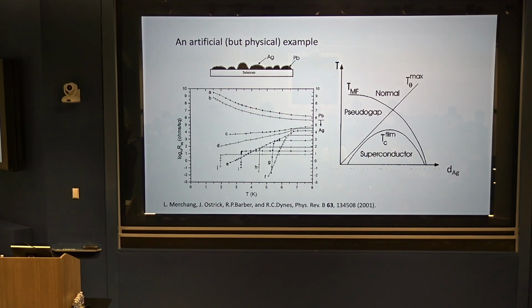Okay, so there is such a material. There's YBCO 247 or something like that. It's got YBCO cuprate copper oxygen bilayers, then a single chain layer, bilayer, and then a double chain layer. Okay. So it's sort of halfway between 123 and 248, and that does have unequal dopings. And under a little bit of pressure, it also goes up to 110 Kelvin. But it's also got lots of other differences. Again, I'm not sure I'm prepared.